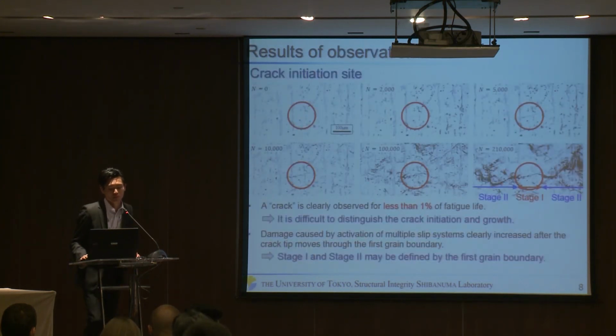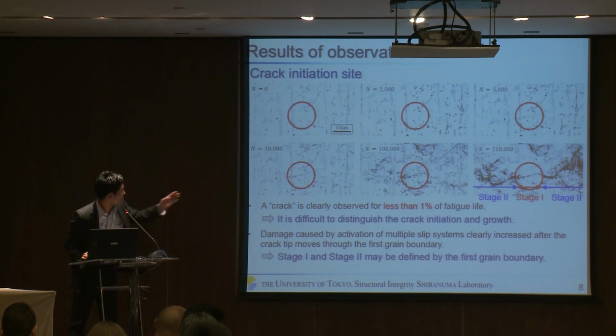And this is the result obtained from the crack observation. As you can see, crack propagation seems to occur at the very early stage, and crack initiation can't be clearly distinguished. It indicates that crack propagation may be more important than crack initiation is. And as you can see, there are multiple slip systems in the last picture. So we focused on the first grain boundary. So in this model, stage 1 and stage 2 are defined by the first grain boundary.